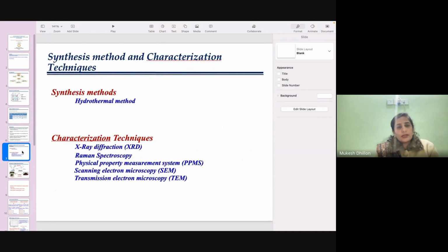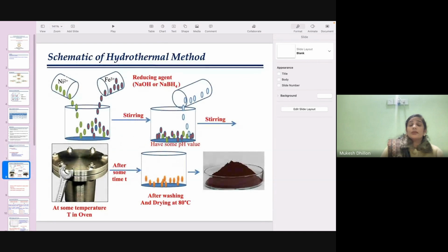Synthesis method and characterization techniques used. I use the hydrothermal method for the synthesis, and the characterization techniques used are XRD and Raman spectroscopy for crystal structure formation, physical property measurement system for magnetic behavior, and SEM and TEM for morphology. This is the schematic for the hydrothermal method. First we take the nickel salt and iron salt in 1:2 molar ratio. After stirring, we add the reducing agent for maintaining the pH value. I use two types of reducing agent here, NaOH and NaBH4. After stirring for half an hour, we put the solution in the autoclave for some time T and at some temperature T. I fix the time at 12 hours, but vary the temperature of the oven.